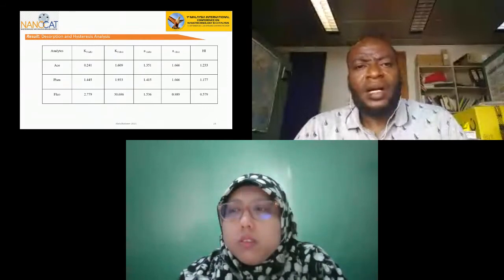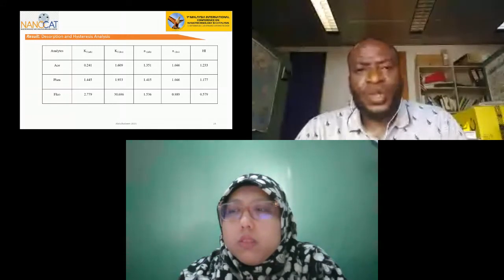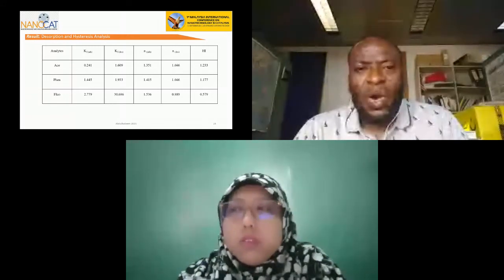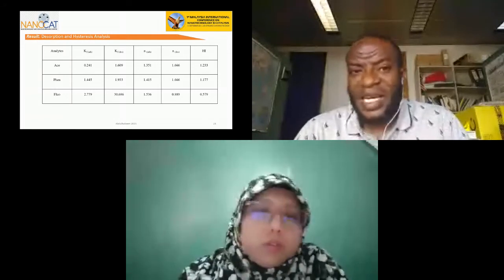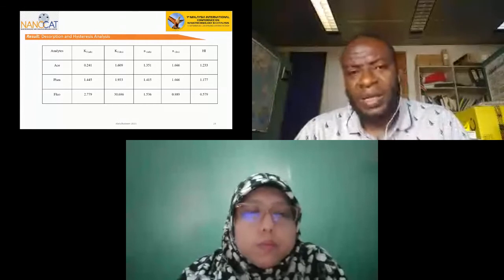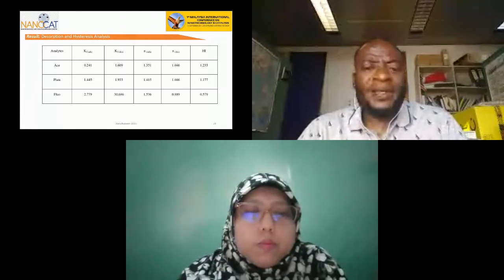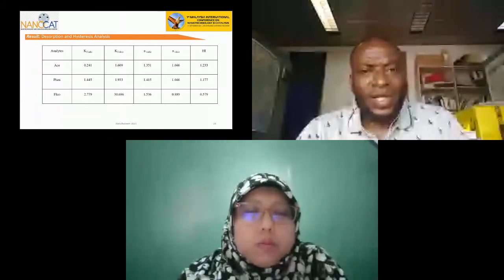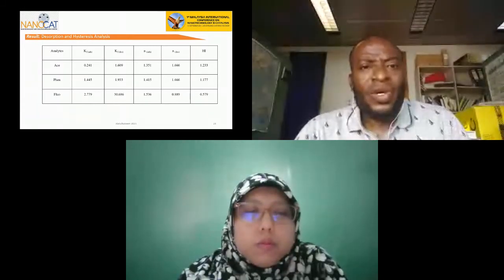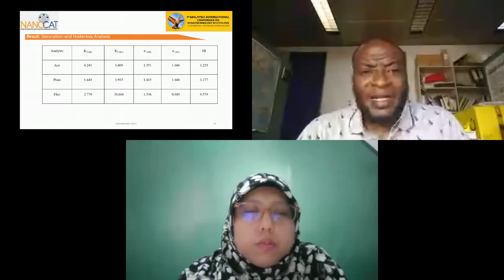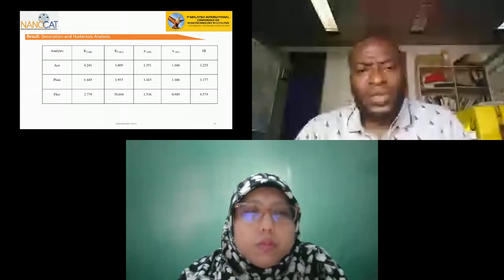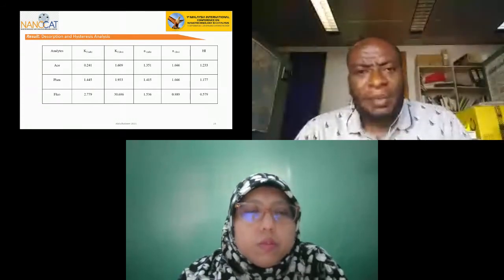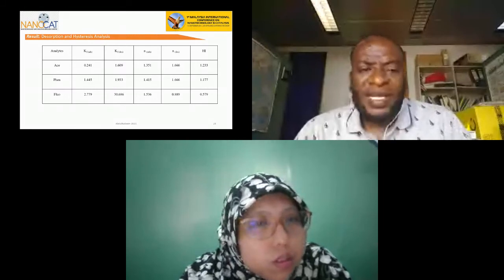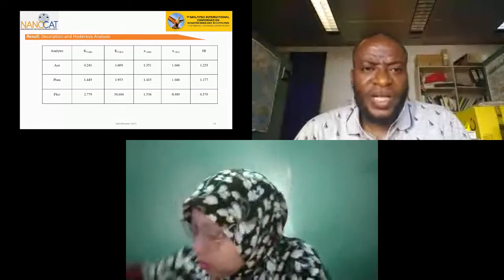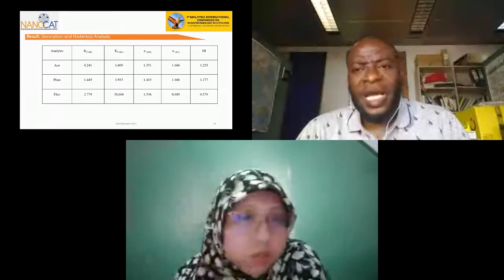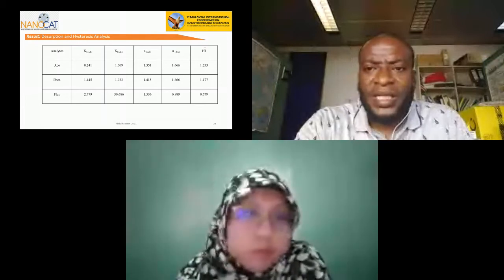Recently, the scientific community has been having interest to know the contamination tendency of any adsorbent to release some of the adsorbate back into the parent solutions. And one of the experiments to determine this is called hysteresis analysis. They really want to know, is it possible for the adsorbent to recontaminate the parent solutions? They do this experiment to determine the potency of any adsorbent to hold the adsorbate strongly so that there will not be any recontamination. And the value they normally look for is the hysteresis index.